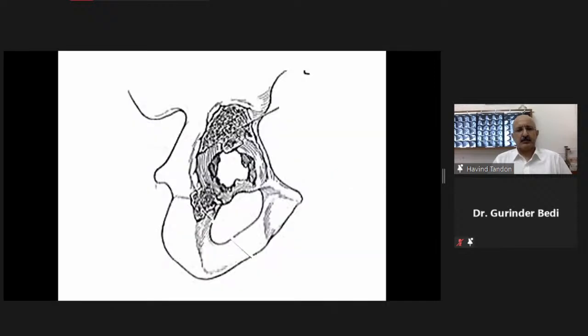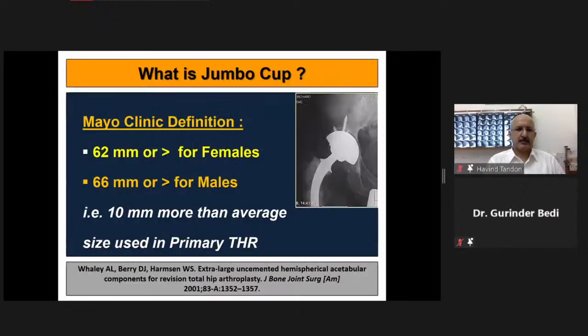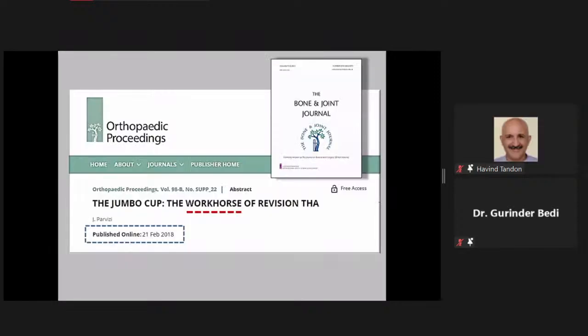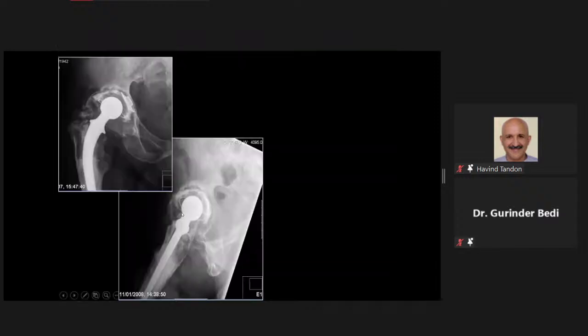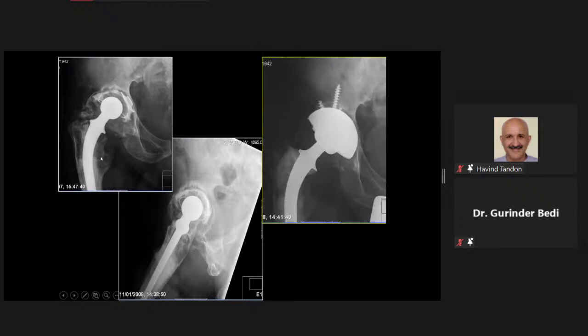Now, if you do not want to use these augments and supports in a case where the acetabulum is worn out and oblong in shape, one can ream it to a spherical shape and use the so-called jumbo cup. This is the classical definition of a jumbo cup. This is considered the workhorse of revision total hip arthroplasty. Just sharing one example with you. In this case, for revision, a cemented stem was used and a jumbo cup was used.